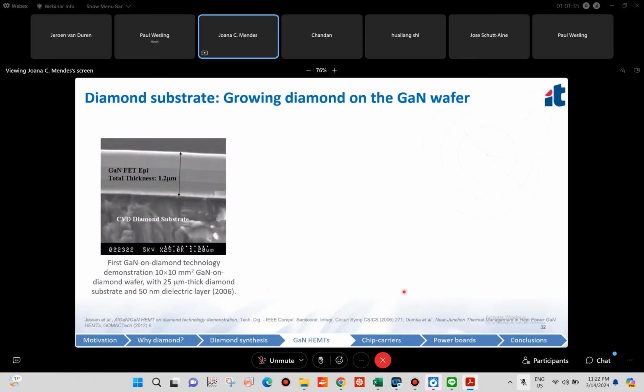And here you see the first technology demonstration that was shown in 2006, where researchers from Group 4 Labs grew 25 microns of diamond on a gallium nitride wafer using a 50 nanometer dielectric layer.